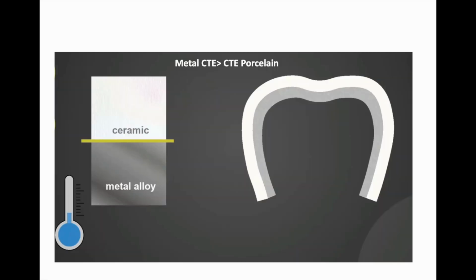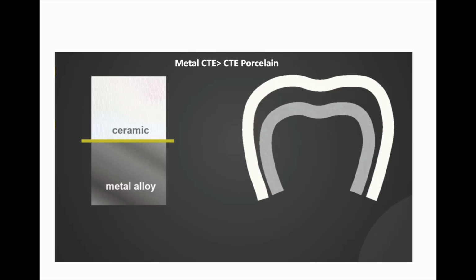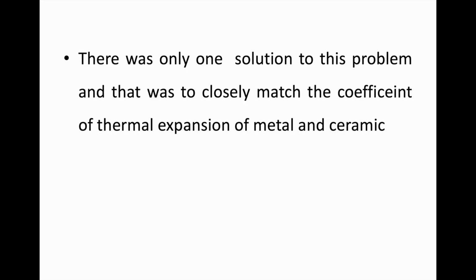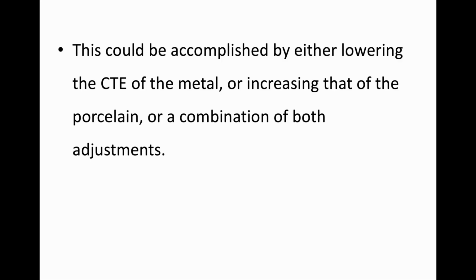This happened because the metal exhibited a very high coefficient of thermal expansion, or CTE, compared to the porcelain. Therefore, as you can see in this video, the metal pulled away on cooling after sintering and the brittle porcelain fractured. There was a simple solution to this problem, and that was to closely match the coefficient of thermal expansion of metal and ceramic. There were three ways to accomplish this, either by decreasing the coefficient of thermal expansion of metal or increasing the coefficient of thermal expansion of porcelain or a combination of both these adjustments.